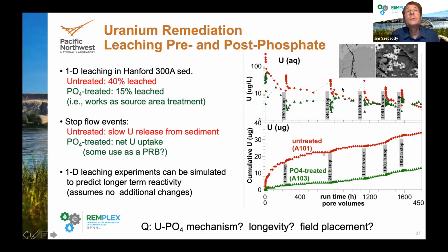So that's in the untreated sediment, but interestingly, in the phosphate treated sediment at these stop flow events, you actually see the uranium concentration decrease. So it's the same sediment and uranium is still being released, but because there's phosphate present, there's actually some uptake of uranium by the phosphate phase. So this is just hinting that this could be used as a permeable reactive barrier.